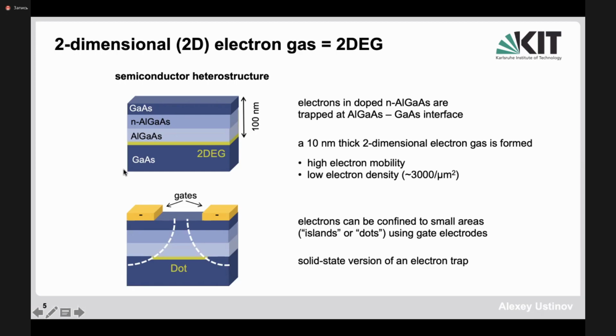And here, basically, you take gallium arsenide as a semiconductor, which is basically a good insulator at low temperature, and then you dope the semiconductor such that the band structure will be bent near this doping layer, and then the Fermi level will be above the bottom of this very thin layer, so that there will be only few electrons entering a very thin layer, which is shown here in yellow. And then you cover this layer by a so-called cap layer, based on differently doped aluminum gallium arsenide, and then cover fully with another gallium arsenide cap. And basically, by using the trick so that you keep the electrons at a distance from your impurities, this would allow them to move freely.